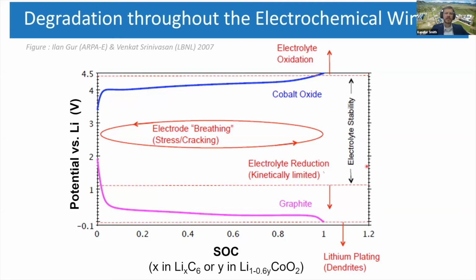First, to describe some of the degradation that occurs all throughout the electrochemical window of the two separate electrodes. So here we have an example positive electrode, and here's a graphite negative electrode. As you go to high voltages, you can start to oxidize electrolyte at the positive. As you go to low voltages, it accelerates the rate of electrolyte reduction. Pretty much the entire operating range of the graphite here is within the reducing area of the electrolyte. So that's always occurring. Fortunately, it's diffusion limited and slows down with time. And then finally, you've got mechanical stresses, which fracture and isolate the electrode.